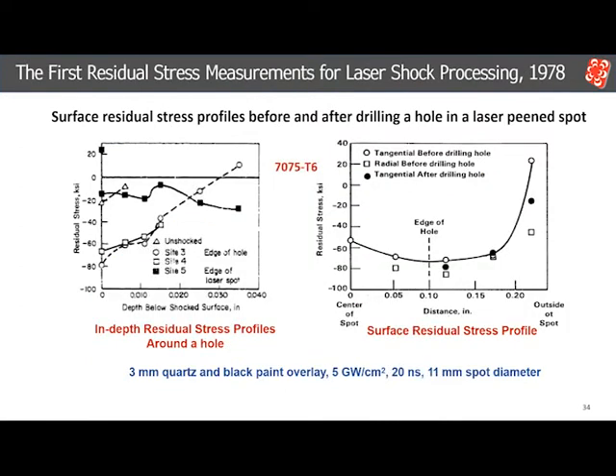Here are the first residual stress profiles of laser peen surfaces. They were measured by X-ray diffraction. On the left are in-depth profiles at various distances from the hole, showing a depth of about 0.7 of a millimeter. The surface stress is at or above the yield strength of the alloy. On the right are surface measurements made before and after drilling a hole in the center of a laser-shocked spot. There was no relaxation of the tangential compressive stress after drilling the hole.